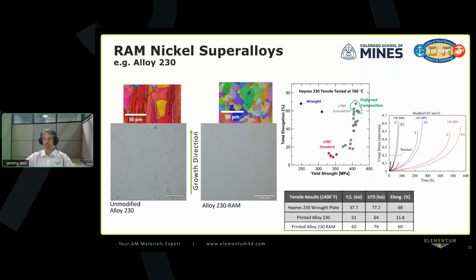This also helps greatly with the properties that you're forming. You can see in that chart, those are looking at the total elongation versus yield strength of different alloy systems. You can see the blue, that's the wrought alloy, so good elongation. But the yield strength isn't nearly as favorable as those gray dots on the right. The laser powder bed fusion traditional alloy as printed, because of those micro cracks, you get poor elongation. The strength is actually relatively good because of the additive manufacturing process. However, the elongation is nowhere near what the wrought is.